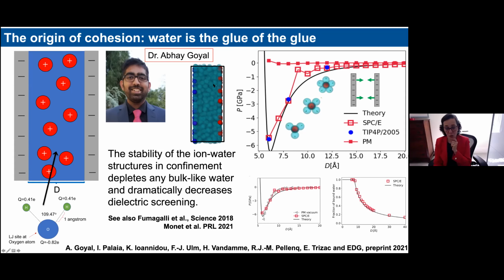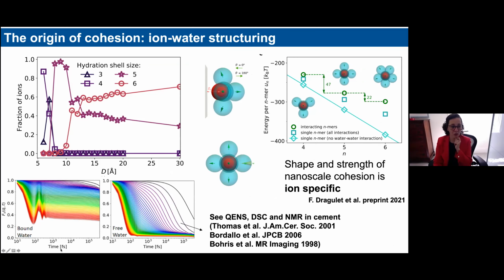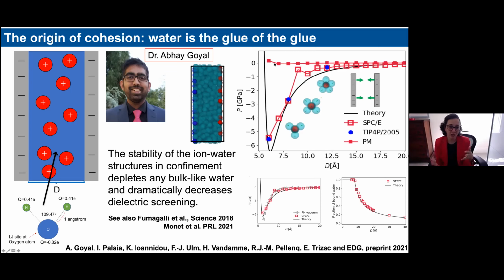So here is the plot of the net pressure that we obtain between the surfaces. This data up here is what you would obtain just from the ion correlation forces I was showing you before, where you consider just the ions in a dielectric continuum with the properties of bulk water. And these instead are the data that you obtain with explicit water. This continuous line is a theoretical prediction for the effective interactions between the two surfaces that we computed with our colleagues in France, considering that the electrostatics should be computed in terms of the ion-water structure that we obtain from the simulation. If we consider these structures, which determine the net electrostatic interaction between the two surfaces, then you obtain forces that follow pretty well the calculation from the simulation.